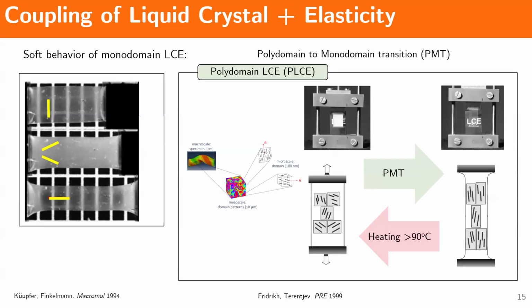Okay, so people also kind of study this material for polydomain LCE as well. And thankfully for polydomain LCE, you also see this behavior, right? So you see the material changing opacity from opaque to transparent, indicating that there's some mesogen orientation and realignment that happens with respect to the loading direction. Okay, and this change is reversible when you heat the material as well. So that's sort of like the idea.